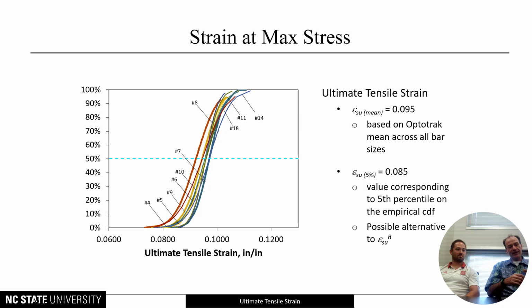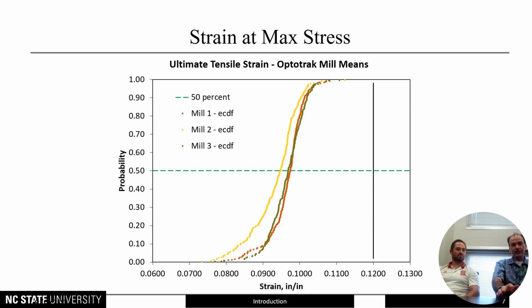So things related to strain and maximum stress, yield stress, ultimate stress, all the typical parameters that you would need. And they were expressed statistically. So there was variation, of course, with bar size for all these different parameters, including the strain at max stress, so the ultimate tensile strain. That's one that was lower than what you'd expect for Grade 60 steel, but we felt good enough. It was high enough. It was sufficient that there was promise to use this in seismic design of bridges.